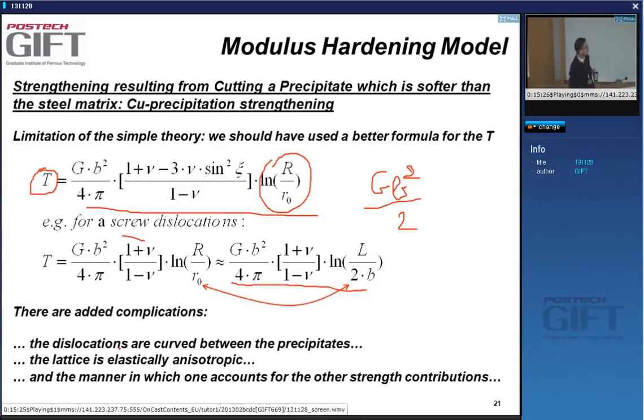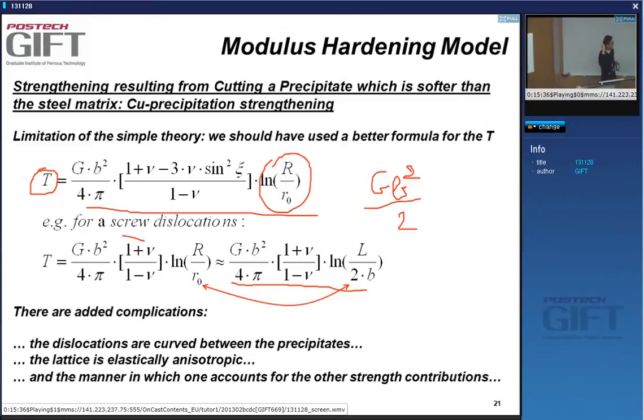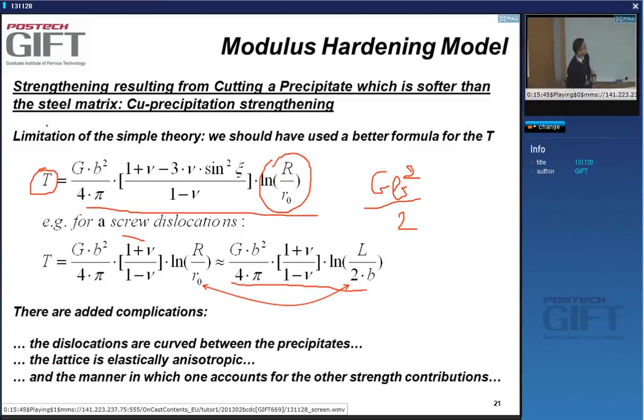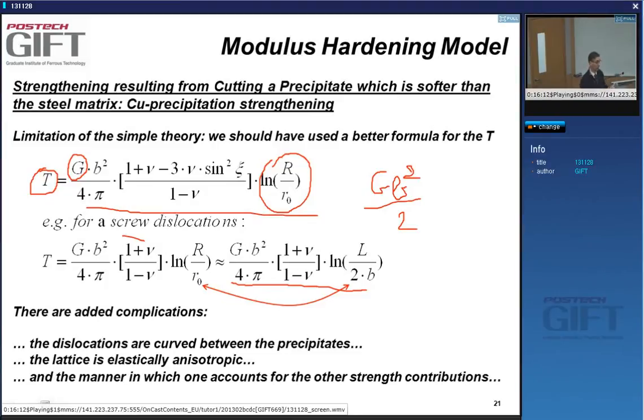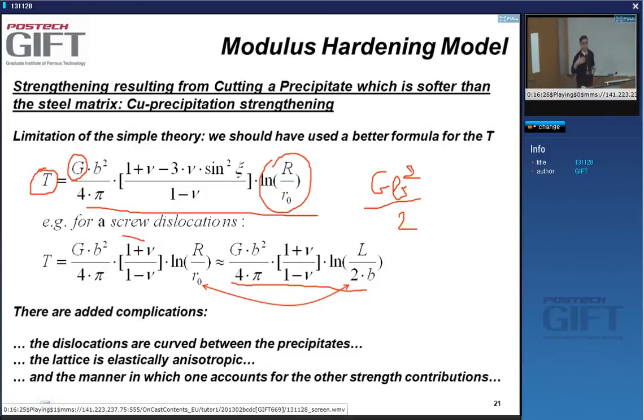There are added complications: dislocations are curved and not purely edge or screw. Our lattice, certainly iron, is not isotropic — by using one value for G we assume isotropy. And when you have a strengthening situation, there may be multiple mechanisms. For copper in iron, copper has an impact both as solid solution strengthening and as a precipitate, so you need to account for both effects occurring simultaneously.